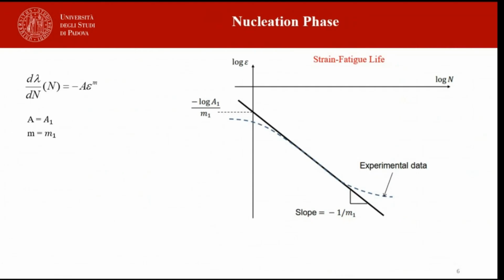In this work, we only simulate the crack initiation. In the nucleation phase, the A and M parameters equal A1 and M1 and can be obtained from the SN data. From the slope of the logarithmic curve of number of cycles versus strain, we can calculate M1, and parameter A1 can be obtained from the intercept of this line with the strain axis.